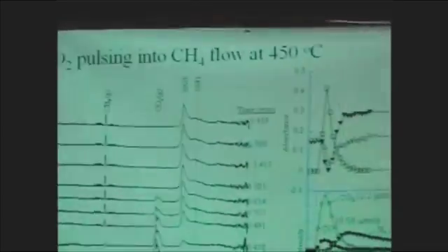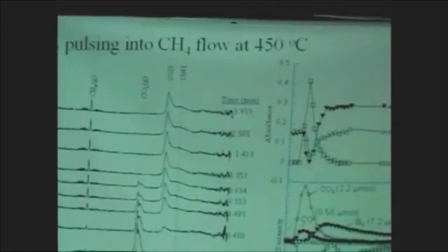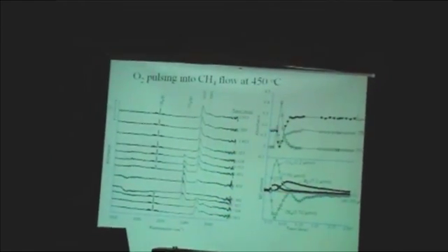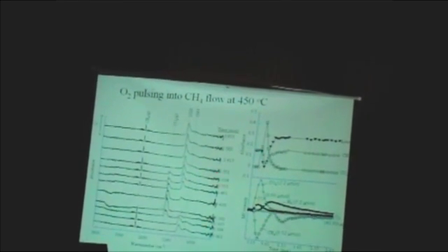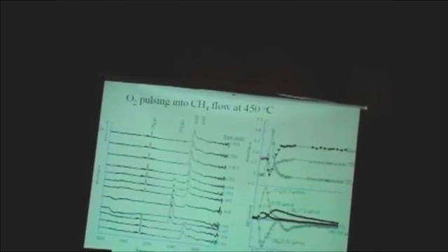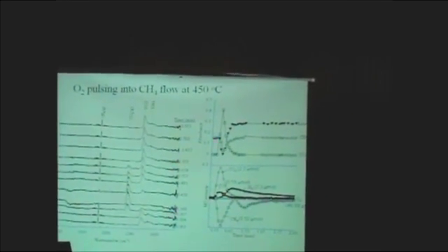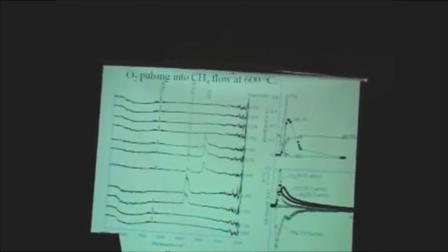And the CO concentration here certainly is much lower than the CO concentration in the reforming of methane with CO2. So there is a different amount of adsorbed CO and adsorbed oxygen on the catalyst surface here. So the CO formation is much easier in the partial oxidation. And this is at a higher temperature. Again, if we move the temperature higher, we still see the hydrogen is being produced behind the CO here.